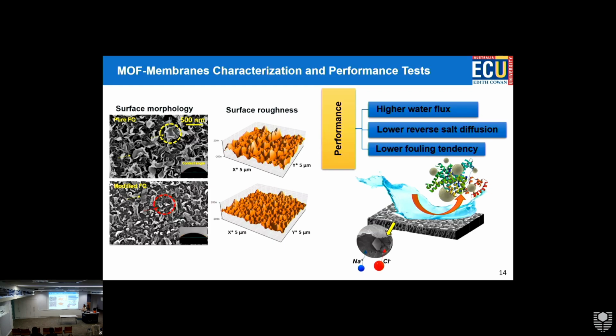And the AFM images, atomic force microscopy images, showed that the roughness decreased after modification. So as I mentioned, if we have less roughness, we have less fouling, all right? Because we don't have those active sites that contaminants get attached to, basically.